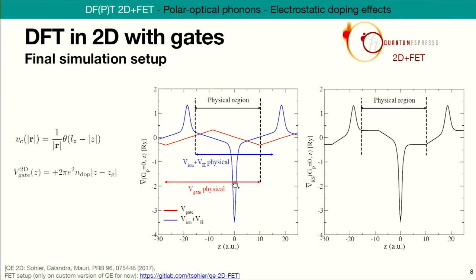And this is here in blue here. Now you have the potential generated by the gate, so oppositely charged. Again, a linear thing, but the opposite slope. All makes sense. If you add the periodic boundary conditions, then it becomes a sawtooth potential. And here again, it has a finite region in which it's physical. Now, you can take the overlap of those two physical regions, and that's where the sum of the potentials, so the total potential, will be physical. And this is what you get here. You get exactly what you're supposed to get for a field effect transistor kind of setup, with, outside of the physical region, some bumps and some weird things that are not physical, but we don't care about them because the electrons are going to stay within this region and they're not going to explore those unphysical regions.